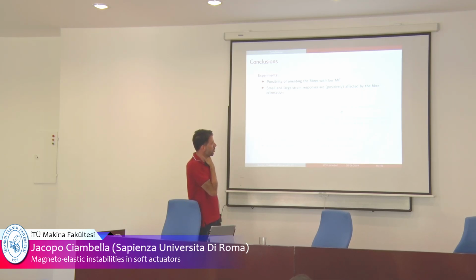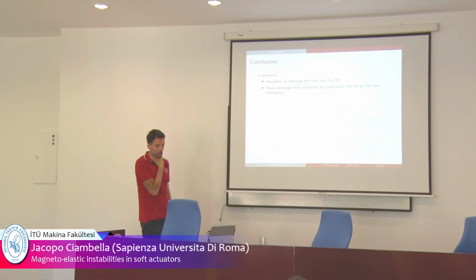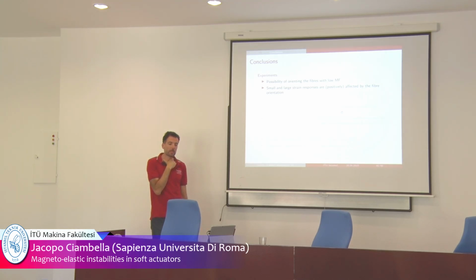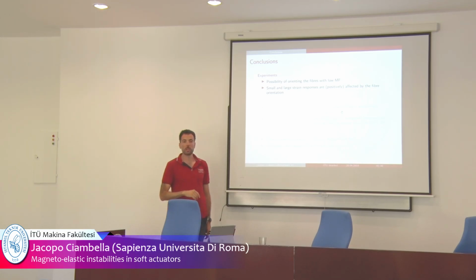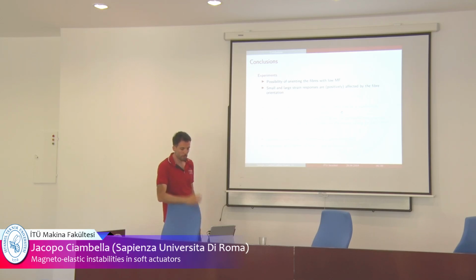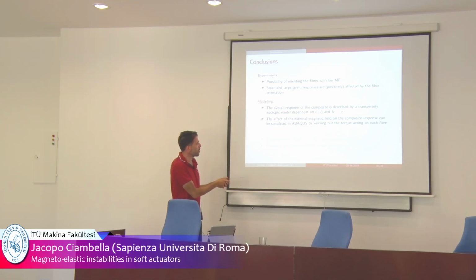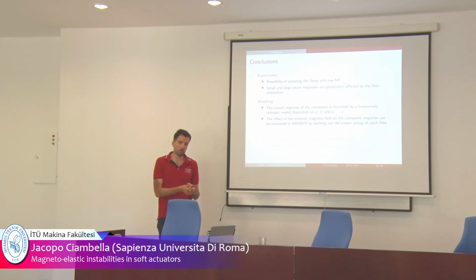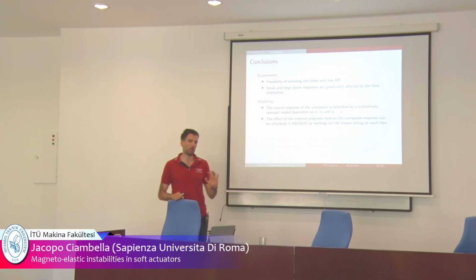So let's conclude here, briefly summarizing what we have seen so far. From the experiments, we have shown the possibility of orienting short nickel-coated carbon fibers with an external magnetic field. We have seen small and large strain effects, strain hardening effect. Then from the modeling point of view, a nonlinear model which depends on I1, I2 and I4 is enough to describe the experimental behavior. And in theory, you can introduce the effect of the magnetic field in Abaqus or in other software to describe complex deformation. The deformations we have seen so far are very simple.